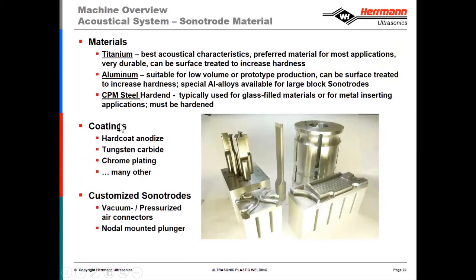The different materials that we typically use are either titanium, aluminum, or steel. I would say about 75 to 80% of the tools that we make are made of titanium. And then the other, 10% in aluminum and 10% in steel, plus or minus. Titanium has the best mix of strength and elasticity. Aluminum is very soft, so it can have more amplitude or it can be stretched more than titanium. However, because it's softer, it can wear out faster as well.